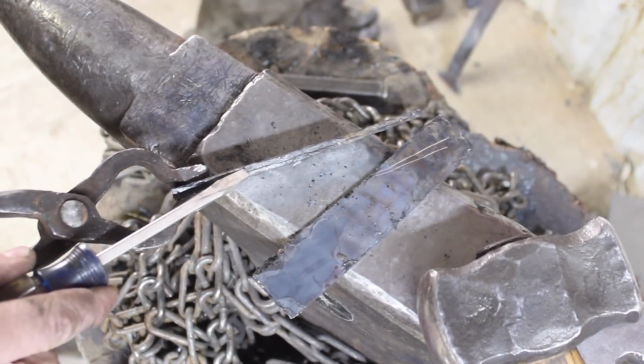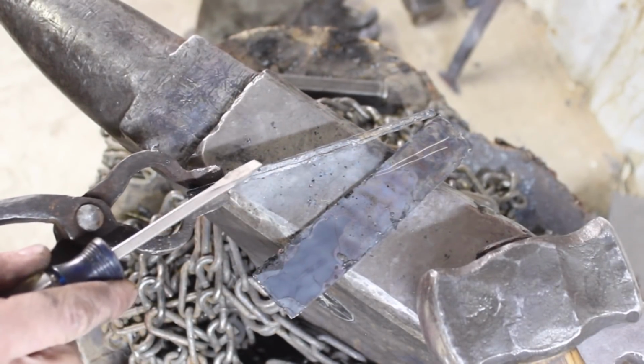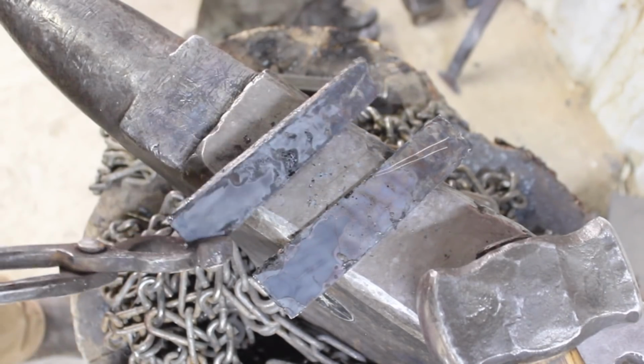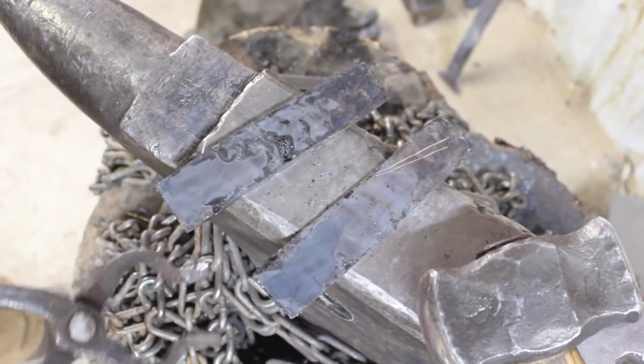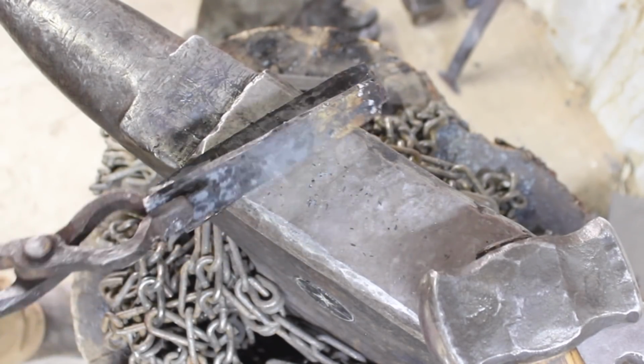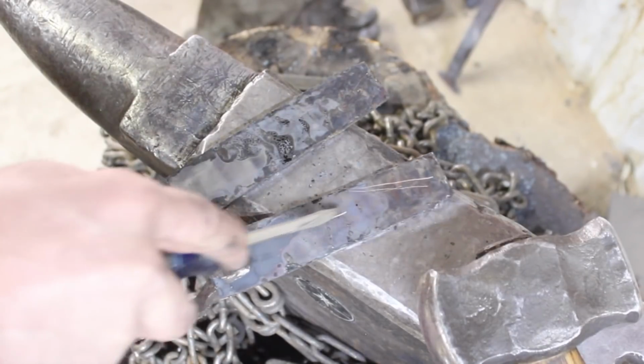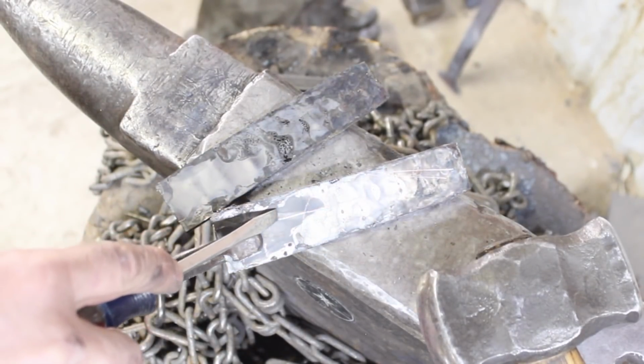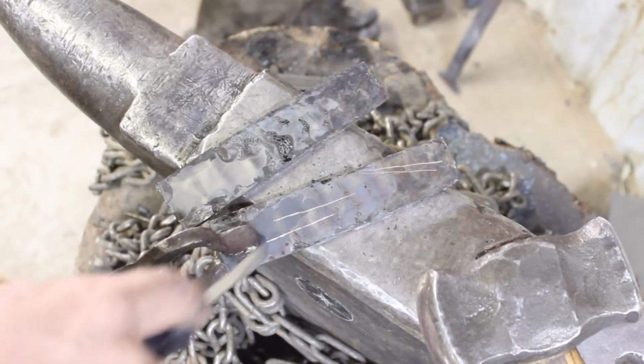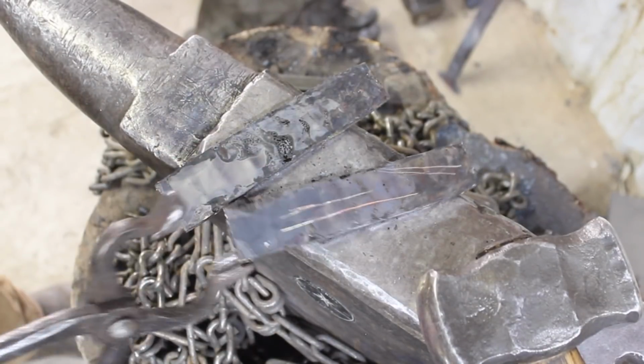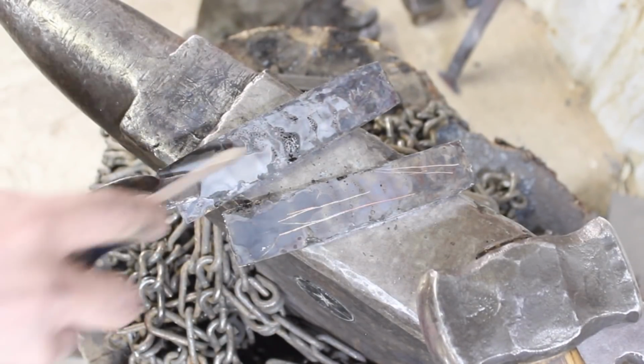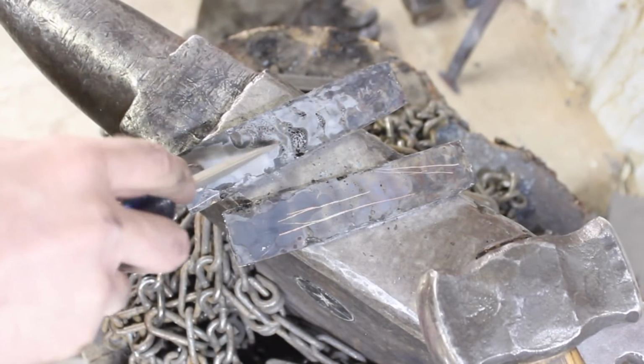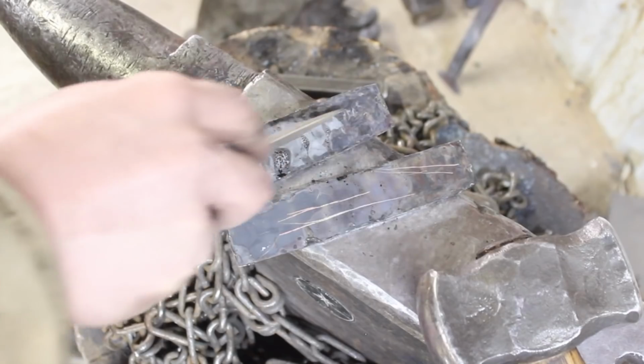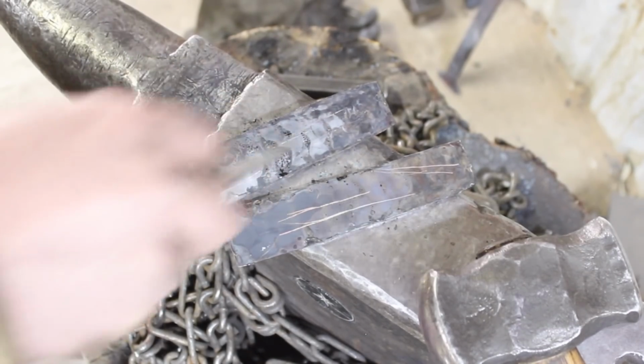So what we have here is my 1075/15N20 on the left, and then my 52100 steel, and then on the far right is another 1075 and 15N20 sheet. So you can see that scratching it here, you get a nice soft reaction in a copper color. That's where the copper is. And then over here on the 52100, there's a few spots where the copper bonded, but primarily there's no copper on there.